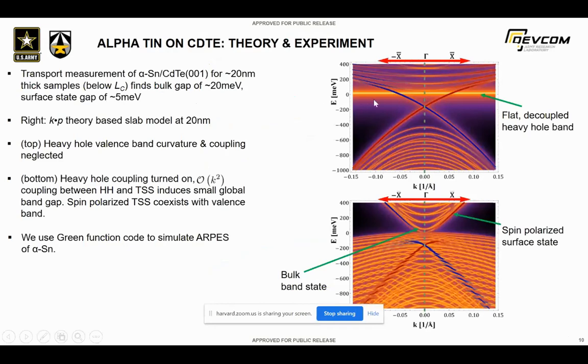So now this slide, this is some more theory that was done by George. Shown here are theory simulations of ARPES measurements, in other words, angle-resolved photoelectron spectroscopy data that can be simulated by theory. These are typical measurements that one uses to see the band dispersion at the surface of these materials. George's theory is able to use the Green's function technique to simulate ARPES measurements of alpha tin.